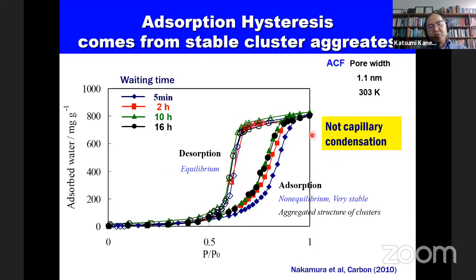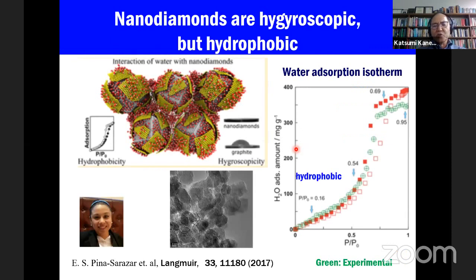That means this adsorption branch, according to the simulations, the water molecules, as already mentioned, form clusters. Clusters are very stable. Those clusters form an aggregated structure. Those aggregated structures are also very, very stable. The total energy difference from the almost continuous water stable structure is less than 2 kJ/mol, very small. Then they form a very stable non-equilibrium structure. So water has very, very unique adsorption behavior.